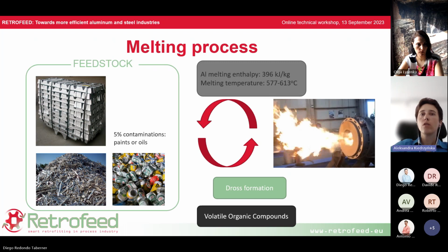Aluminium feedstock consists of ingots and scraps. Ingots are quite clean aluminium, but scraps are recycled and can contain up to 5% of contamination, such as paints or oil. When they are inserted into the furnace, those contaminants are intensively released as volatile organic compounds and are combusted in the furnace. This also increases the dross formation. The dross is a byproduct which decreases the product quality and efficiency.